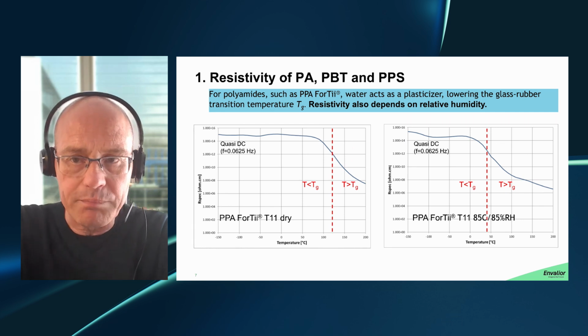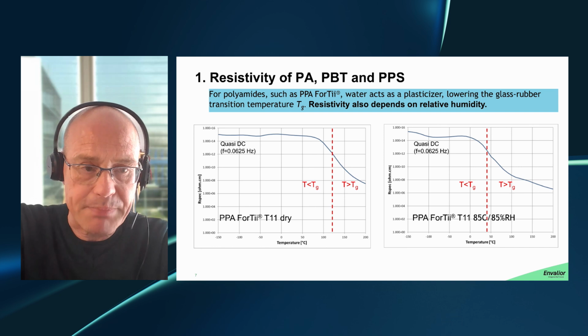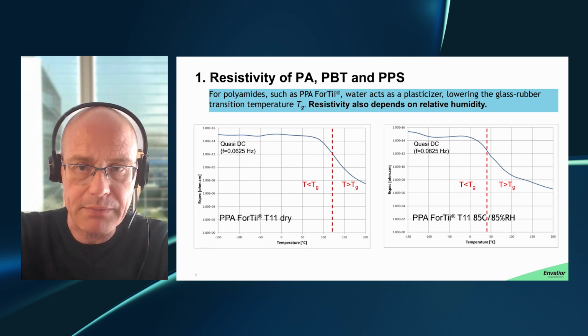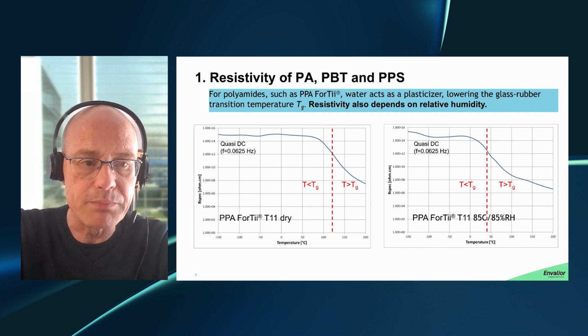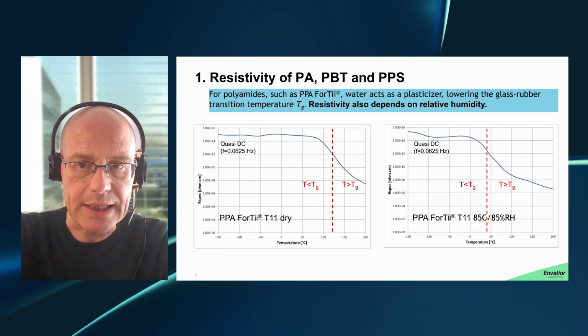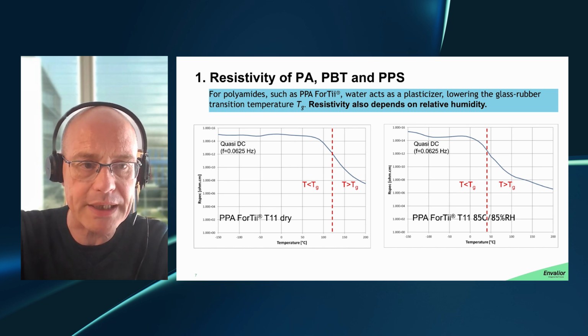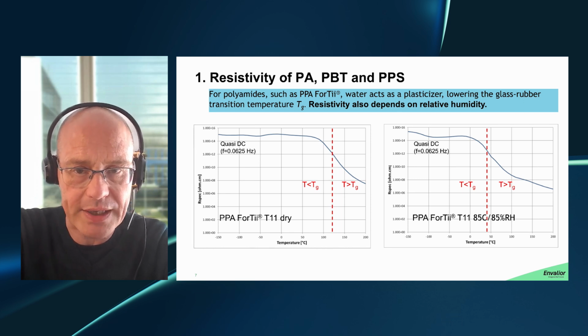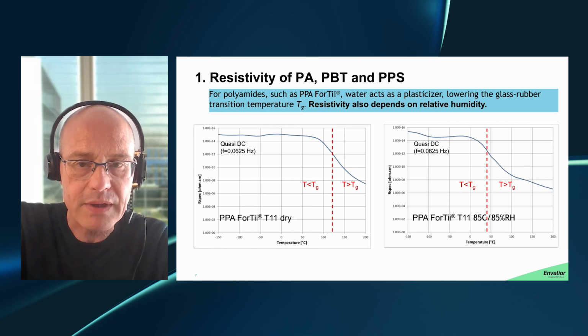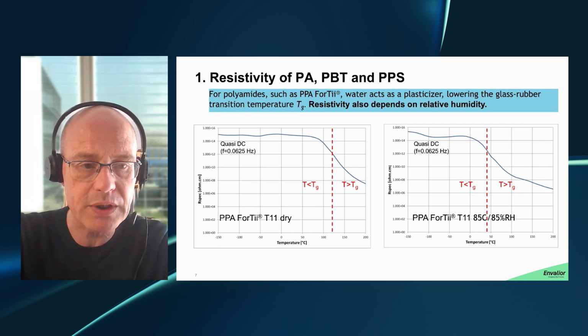Now, for the case of polyamides, such as PPAs, but it goes also for all the other polyamides, the resistivity is also a function of the relative humidity of your local environment. And this is related to the fact that water is taken up by these polymers. It acts as a plasticizer, and it tends to lower the glass transition temperature of the polymers. And therefore, it affects this transition from a, let's say, glassy electrical response to a rubbery electrical response.